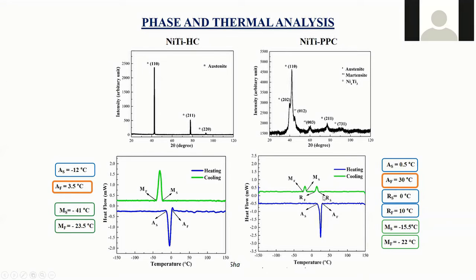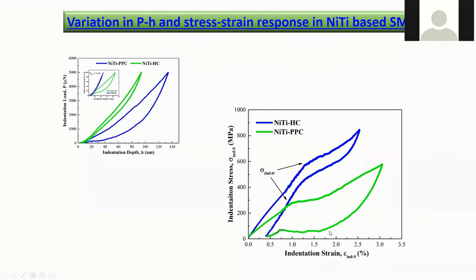Whereas if we have some precipitates in it, the austenite finish temperature is very close to room temperature, which means that there is a possibility that the austenite transformation is not yet fully done at room temperature. If you're considering 300 K, maybe the austenite finish is not yet complete. And this can be reflected in its indentation behavior as well. As you can see, this P-h curve is completely different. The blue one is for the solutionized one, and the green one is for the precipitated one. And we see completely different behavior.